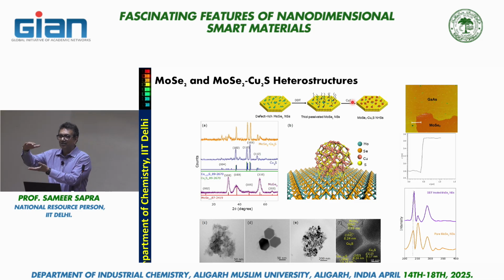When it's absorbing blue, it's a smaller band gap. When it's absorbing green, it's even smaller. Particle size is growing in that direction. So you all have made nanoparticles even long before you've known that. Okay. So Shamim put some cuprous iodide, and it has so much affinity for sulfur that it reacts immediately, and it forms these kind of heterostructures. If you look at these TEM images, these are molybdenum selenide sheets, and on top of that you have cuprous sulfide.